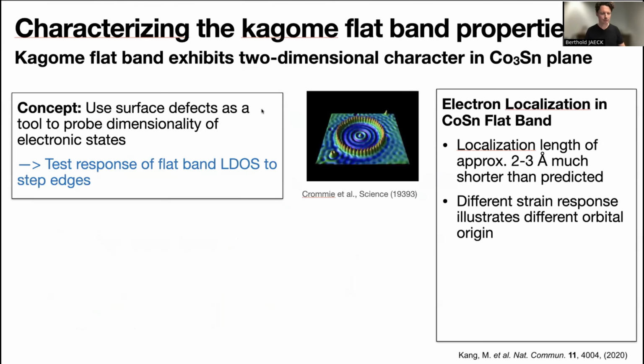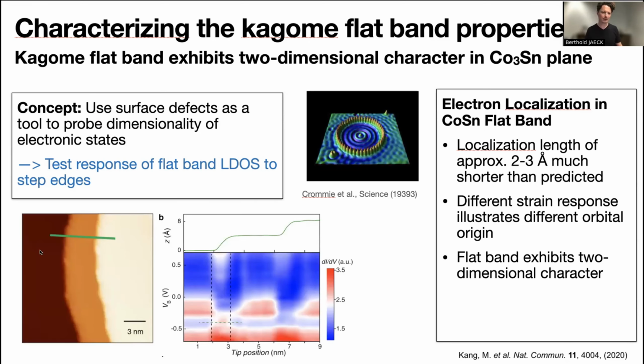Right. So before I come to the end, of course, we ask ourselves, how can we further characterize the flat band properties? The first thing we said is, look, we can essentially now use surface defects to test for the dimensionality of these states. We all know, or we are aware of this very famous example by Mike Crommie and his co-workers back at IBM, when they used this quantum corral to visualize essentially these standing wave patterns of free electrons. And we kind of took on this idea to now use surface defects on the surface of cobalt tin, in our case step edges, to study the dimensionality.